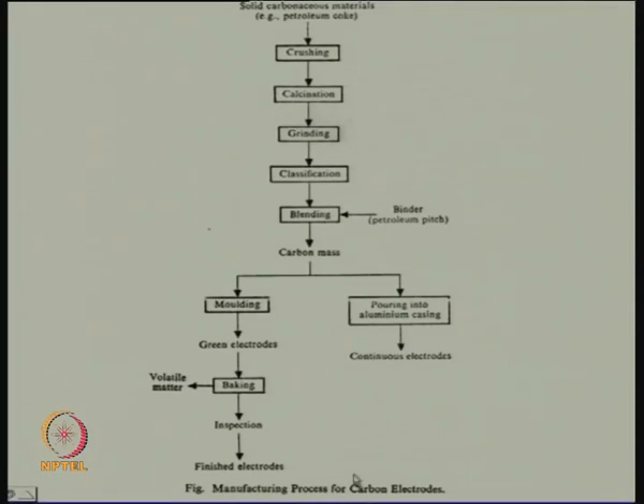Aluminum electrolysis has a cell that is continuously being fed by alumina. It has to be continuously fed by graphite also for making an anode which is consumable. And the manufacturing process for carbon electrodes is a very elaborate thing. I have given a flow sheet: you take solid carbonaceous materials like petroleum coke, very pure, crush, calcine, grind, classify, and blend with petroleum pitch so that it can be given a shape. Then you get a carbon mass, you mold it, you get green electrodes, they have to be baked, they have to go for inspection, then you have finished electrodes.